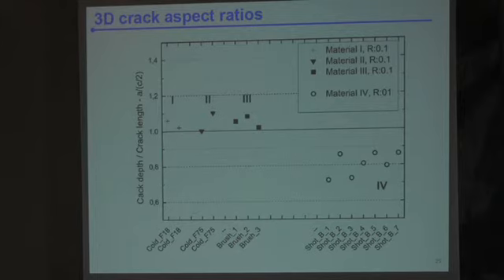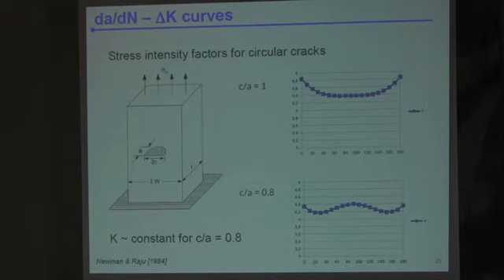So we have no real idea of what was going on, except maybe what you all have in your heads, probably about the variation of the stress intensity factor around the crack front, which is the Newman and Raju typical formulas, right? If you compute the K value along the crack front, this is one surface, this is the other one, this is theta, the angle that describes the whole crack front. In the interior, your stress intensity is lower than at the surface if your crack aspect ratio is 1, and if you go to 0.8, this is more constant. Well, it's not perfectly constant, right?